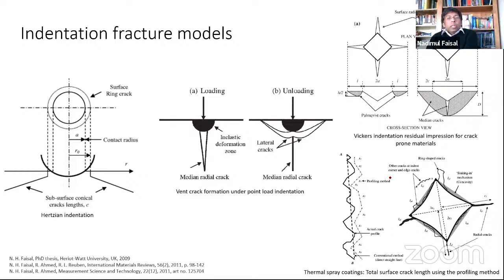If you want to use a fracture model, these are some of the fracture models. You can see Hertzian indentation is very well known. Then median radial crack, median in loading, you can see this is what type of crack. When you unload, then you can have lateral cracks which can pop up. And there are 2 different crack types, Palmqvist and median crack.